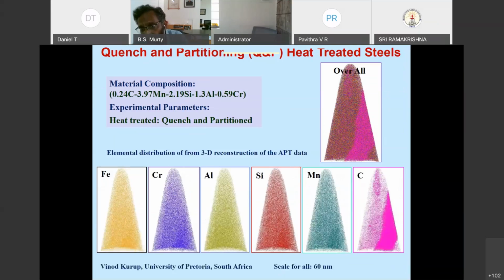People are also interested in looking at steels, for example. A variety of materials people are looking at. For example, they wanted to see whether carbon gets distributed in a particular phase. In steels, we know carbon gets enriched into one phase called austenite and gets depleted in another phase called ferrite, and people are interested to do that. So you can actually see even a very small atom like carbon. The rest of the elements are all uniformly distributed, excepting carbon, which is segregated.